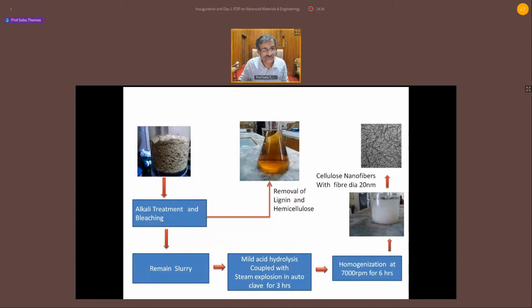We do bleaching. We remove lignin and hemicellulose. We get a slurry, and the slurry is subjected to mild acid hydrolysis or strong acid hydrolysis. If you want to have nanocellulose, long nanocellulose, we subject them to mild acid hydrolysis coupled with the steam explosion. When you go for homogenization, you know what we get? We get the dispersion of nanocellulose in water. And we examine under electron microscope, you see, you get a beautiful network of nanoscale fibers having a diameter of 20 nanometers.